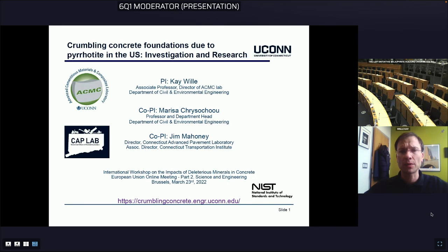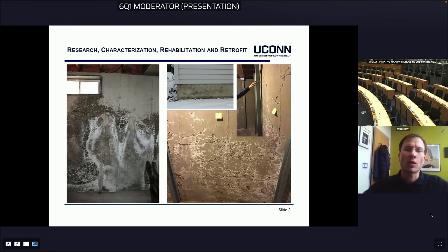Next slide, please. Those are the typical pictures, and you have seen this already. Those pictures are from the concrete foundations here in Connecticut, and those are severely damaged in those cases. Some other foundations are not severely damaged or not damaged at all and still have pyrrhotite in there. Besides the cracking you see here, the typical spider cracking or the horizontal cracking that Nick also mentioned, you also sometimes see efflorescence, or a deposit of minerals, these whitish deposits in the left picture. Next, please.